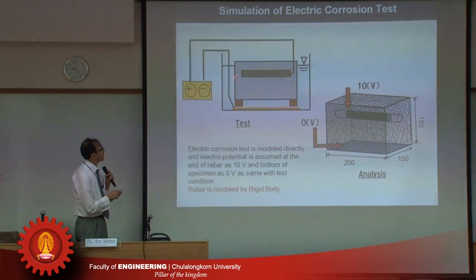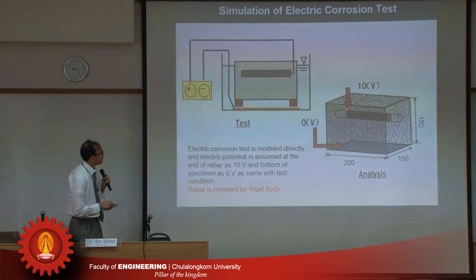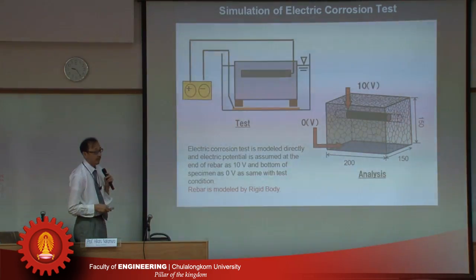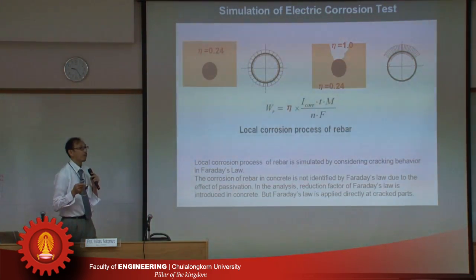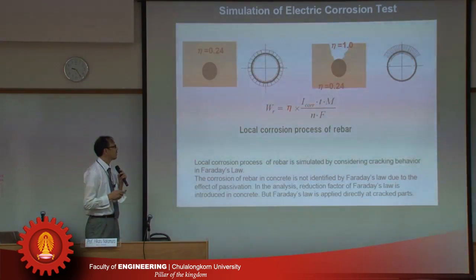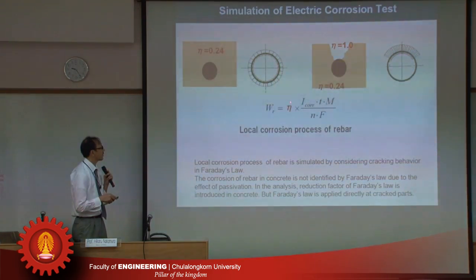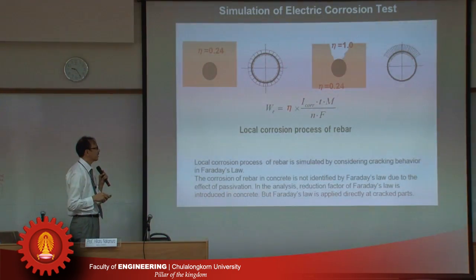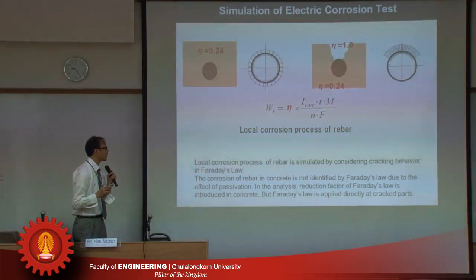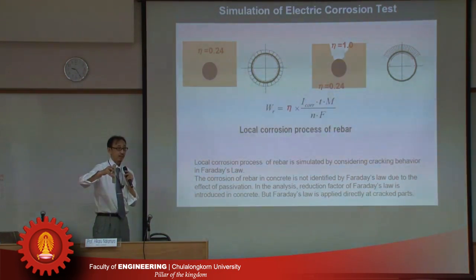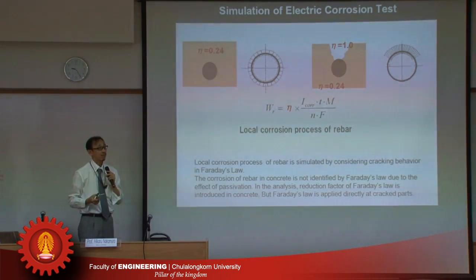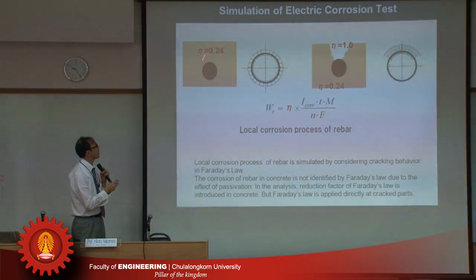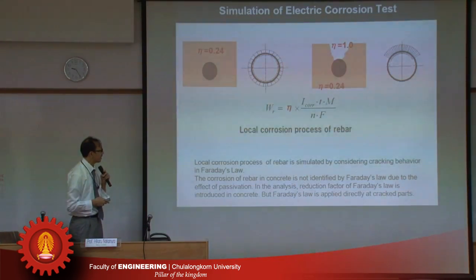This is the analytical model of the test. We consider the electric potentials as boundary conditions, and in this case the rebar is also modeled by rigid bodies. One point of this simulation is how to use Faraday's law. Faraday's law is the key point. But it is known that the corrosion of rebar in concrete is not identified by Faraday's law due to the effect of passivation. Faraday's law can be applied in the atmosphere, but in concrete it cannot be applied directly. So we consider a reduction factor to account for the effect of the surrounding concrete.